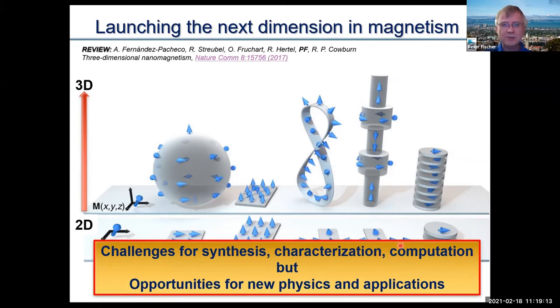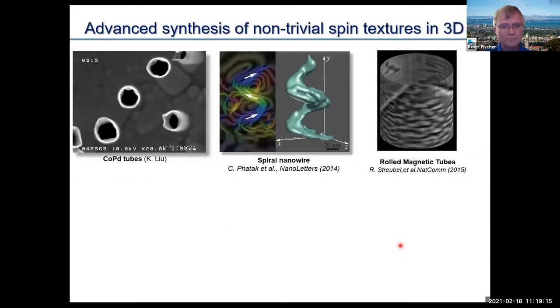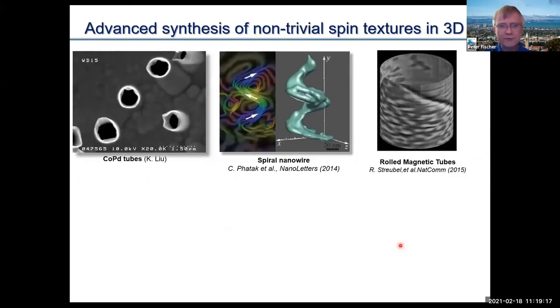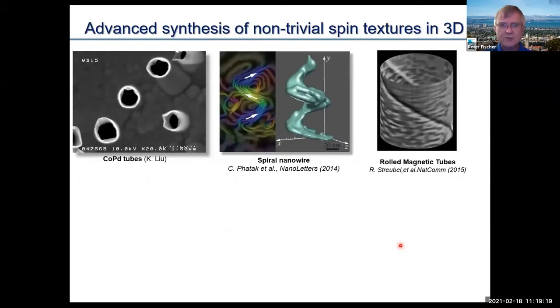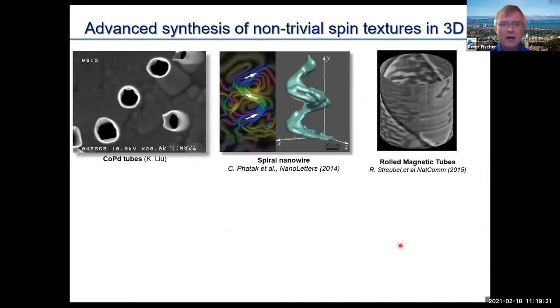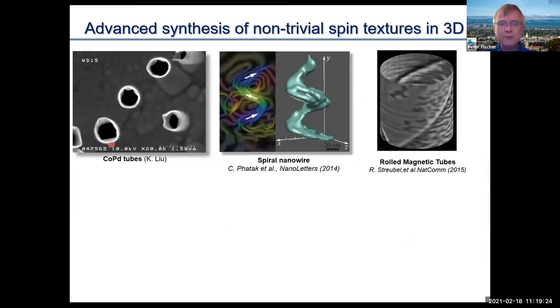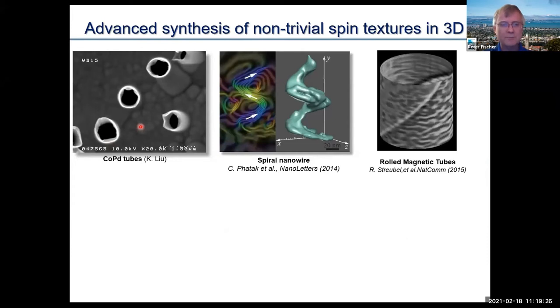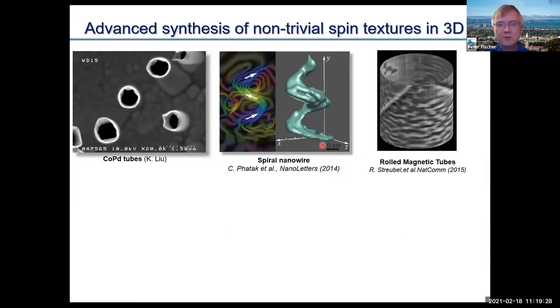And just to show you a few examples of what people have already done, advanced synthesis of those non-trivial spin textures in 3D. Of course, there are nanotubes that are grown by a chemical process, or you can just grow a regular nanowire, but you put it on a tilted substrate and start rotating the substrate while the wire is growing. That means you generate something like a spiral. And this is then electron holography that shows you the spin texture inside this kind of curved wire.